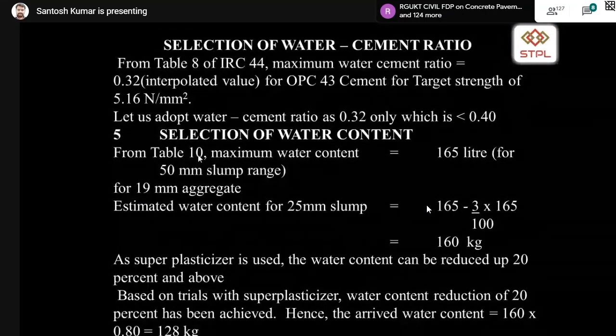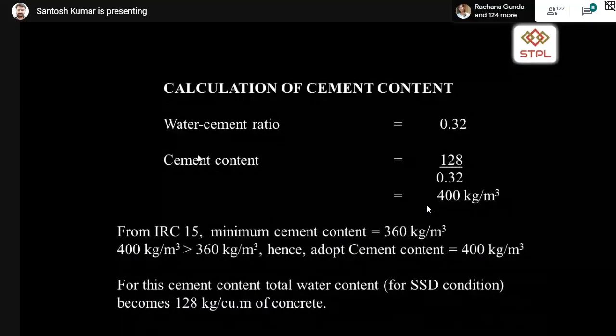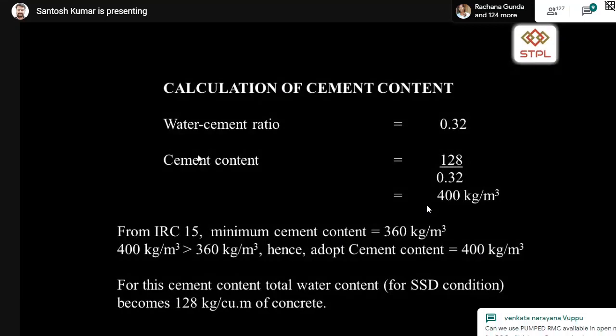Water becomes 160, and when you are using normal super plasticizer, it may reduce up to 20%. So 160 liter again I reduce by 20%. It becomes 128 liter. So again, cement content is calculated by weight of water divided by water cement ratio, which will give you the cement content, which is nothing but 400 in this case. So it is greater than the 360 mentioned in IRC. So the cement content is satisfactory.